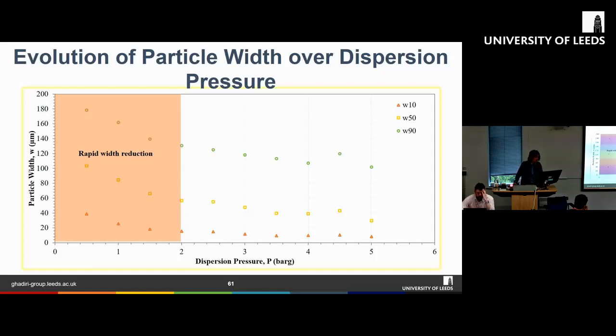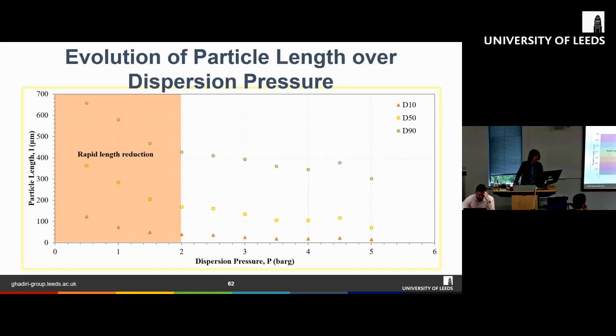You can see that as we increase the dispersion pressure, initially we get a rapid reduction of the width of the crystal, and then after a while it starts to reach almost a plateau. Even though you increase the dispersion pressure a lot, they don't break as much as compared to the initial stage. And similarly, we see the same for particle length, which reduces rapidly initially.